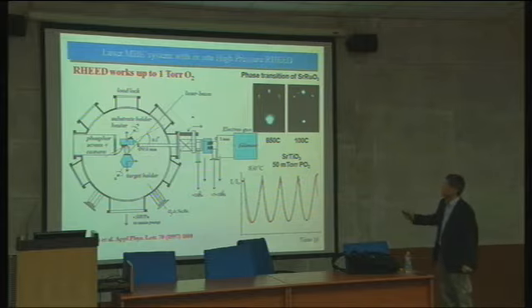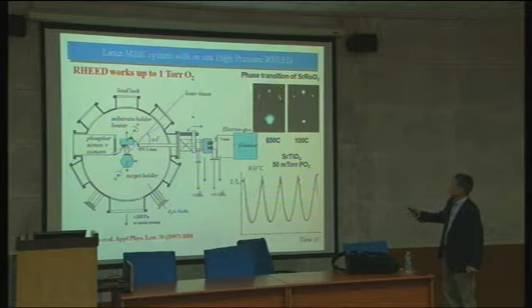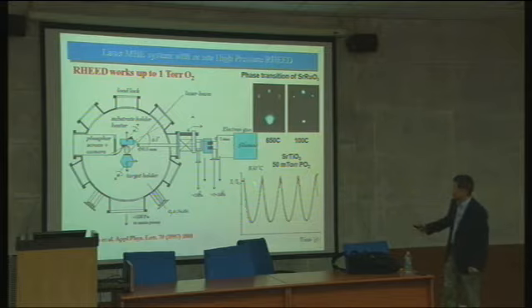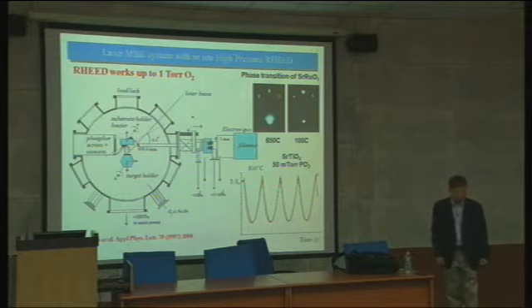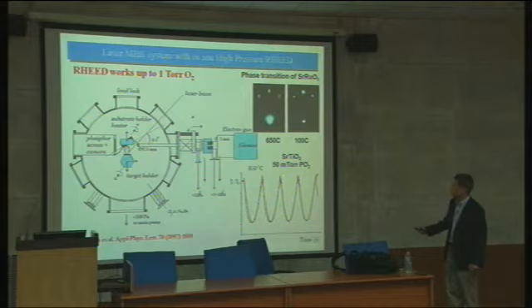And then you can see this diffraction pattern is done at very high pressure. You can see the beautiful pattern. And this is done at 50 millitorr of oxygen partial pressure, growth of strontium titanate. You can see that very nice oscillation. Okay, this is real data.